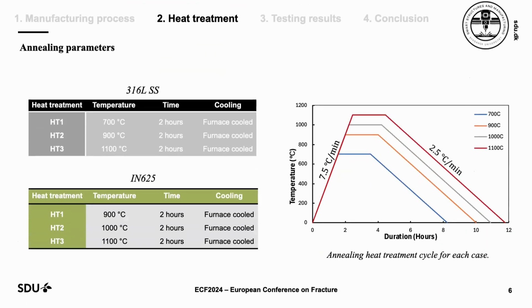The process for stainless steel: we had 3 different cases for stainless steel 316L, with temperatures of 700, 900, and 1100. The time was 2 hours at maximum temperature. The heating rate was 7.5 degrees per minute, and the cooling was 2.5. For Inconel 625, we also had 3 cases for heat treatment, 900, 1000, and 1100. We had the same 2 hours at the maximum temperature, and then it was furnace cooled for different durations based on each heat treatment case.